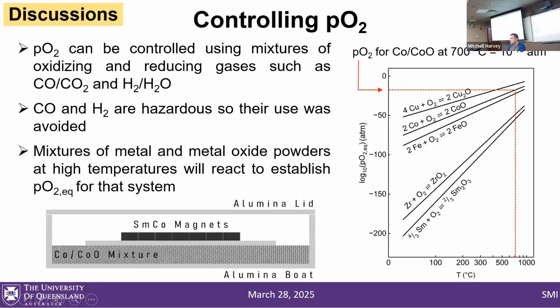They're going to react at high temperatures, and if there's any extra oxygen in the system above the equilibrium value, the cobalt metal is going to oxidize to cobalt oxide. If there's too little oxygen in the system below the equilibrium value, the cobalt oxide will decompose to cobalt metal, releasing oxygen.